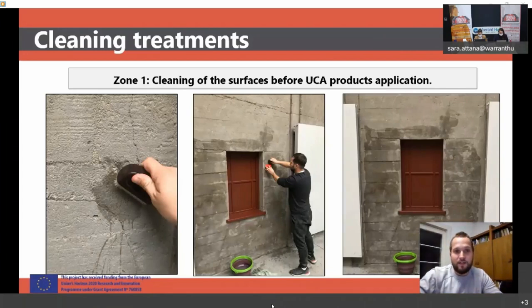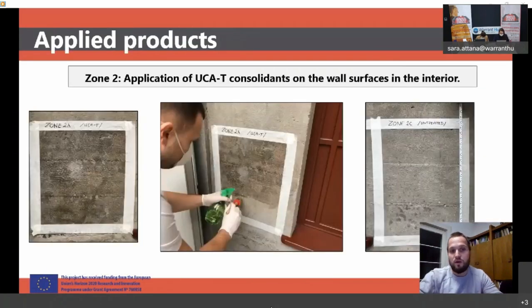So the cleaning treatment was carried out by means of the brush and water, not using compressed air, to avoid blowing the dust into the structure of the concrete, because there was a risk that we could do that. The application was carried out one week after the cleaning process, and the UCA consolidants were applied by means of the brush and spray. And here you can see on the photo how it looked like. And we also left untreated area to compare the results of evaluation of performance.